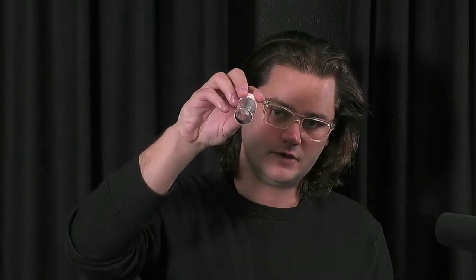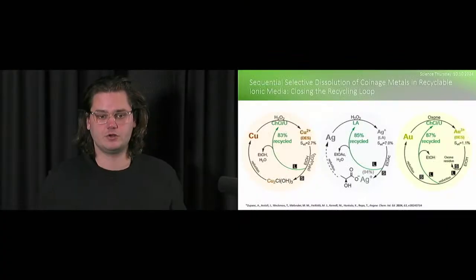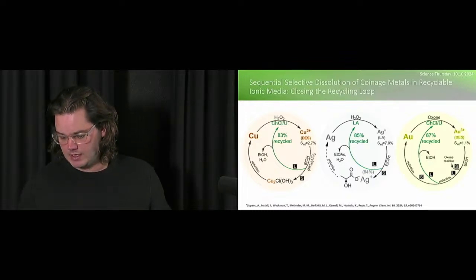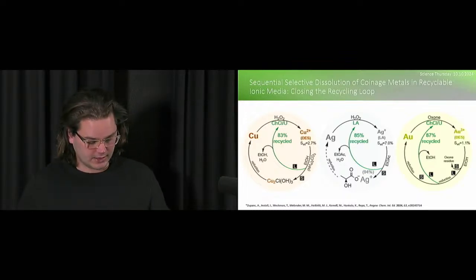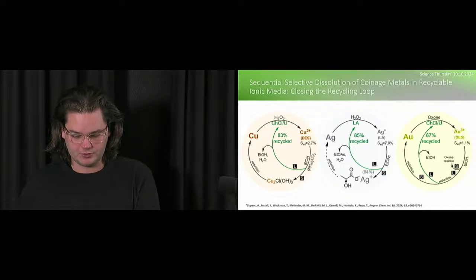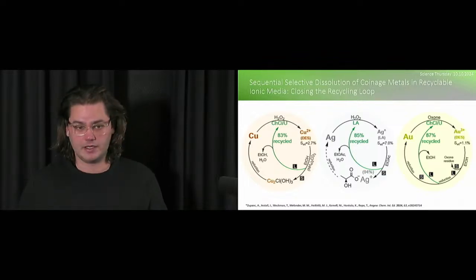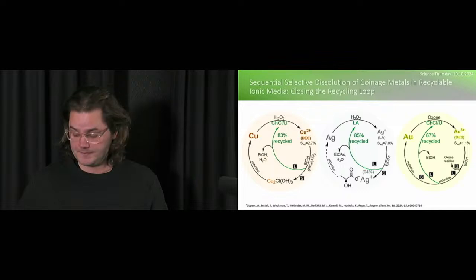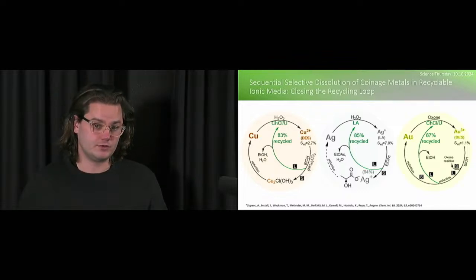After reduction of this copper +1 salt, we can of course get this elemental copper. I don't know if you can see from here, it's this very fine black powder. Of course, how big the particles are really depends very much on the conditions that we were using, but I hope I managed to show you that this process is very easy to reproduce and to do.